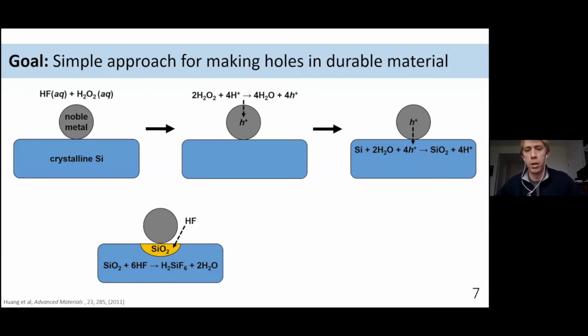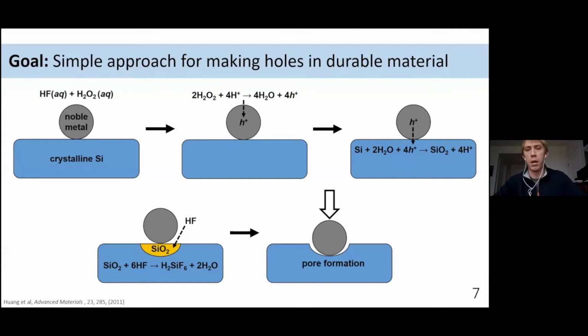So what this does is it eventually forms this little pit on the nanoscale, or essentially the scale of your catalyst particle, that can then continue on to form eventually a very high aspect ratio nanopore as this catalyst particle or feature continues to sink deeper and etch deeper into the silicon wafer in this case. So that's just a very broad overview of the technique.